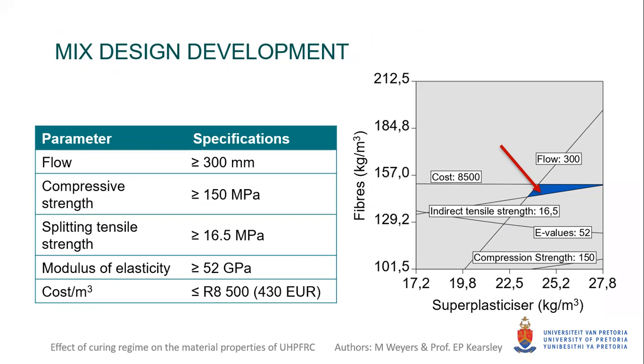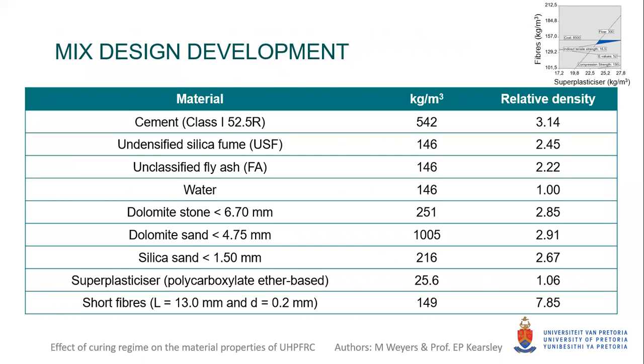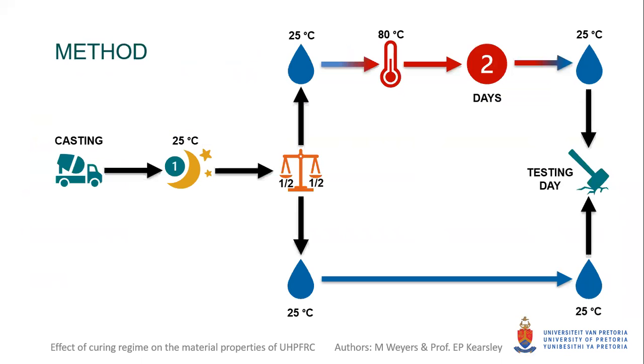The criteria used to obtain the optimum performance is shown in the table. Considering the criteria, an overlay plot was drawn and is shown in the figure with the blue triangle. Any combination of fiber content and superplasticizer content that falls inside the blue triangle can be chosen, and an optimized mixture design can then be obtained. This led to the mix design as shown previously.